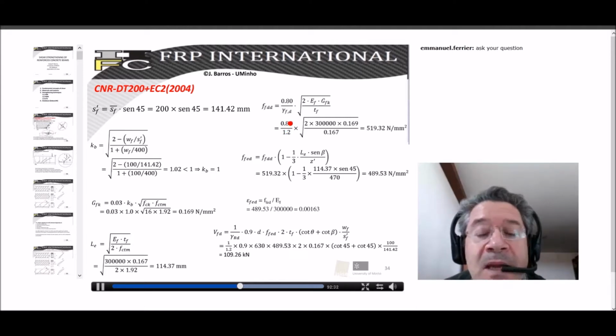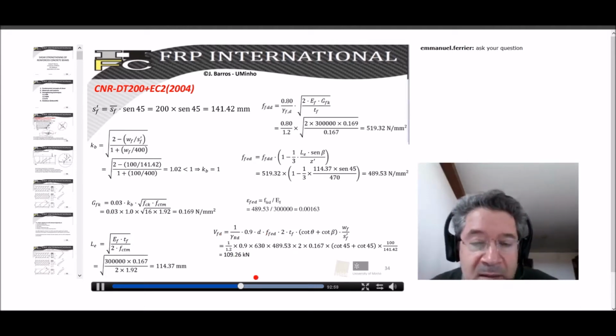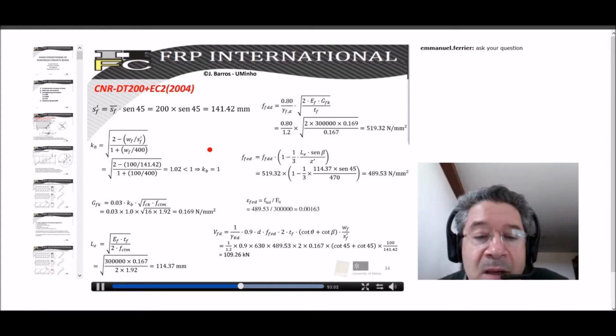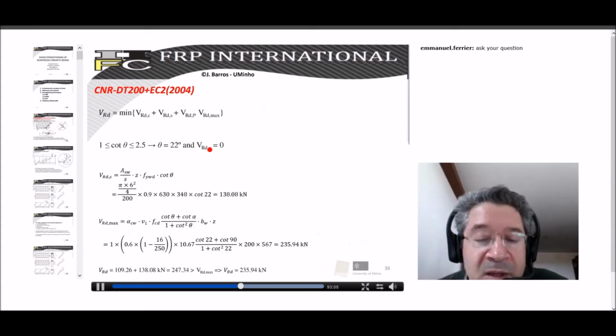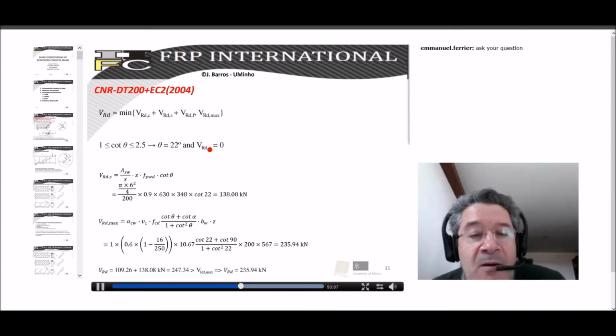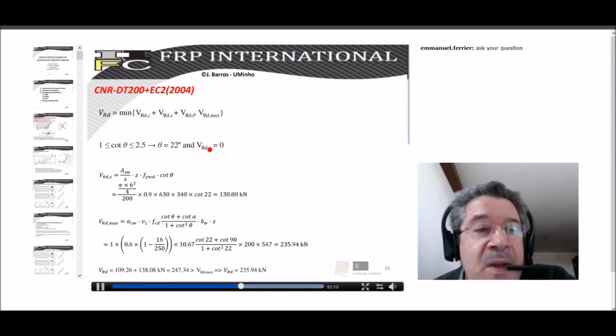Okay, so taking the previous information and replacing in the equation that CNR is proposing to obtain the design value of the effective strain, we obtain a value that is around 490 megapascal. And then if we replace in the equation proposed to estimate the shear capacity of a beam, we finally obtain a value that is around 109 kilonewtons for the contribution of the shear strength beam arrangement applied in the beam.